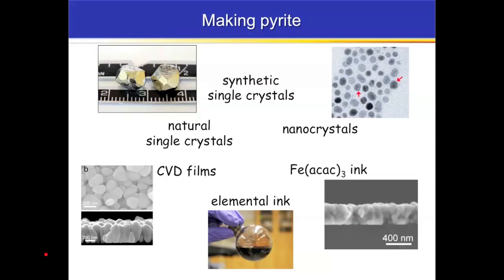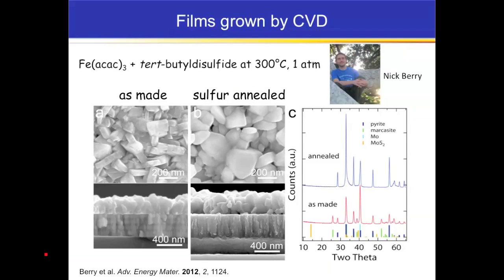So in my group, what we try to do is make a number of different kinds of pyrite materials so we can do comparative studies in order to understand this low voltage problem. We work on a number of solution syntheses to pyrite, including nanocrystals and what we call molecular inks. These are to make thin film polycrystalline pyrite materials. We also do chemical vapor deposition, so we grow it by gas phase. We buy natural crystals, and we also make our own synthetic single crystals using a flux growth technique, which I'll describe.